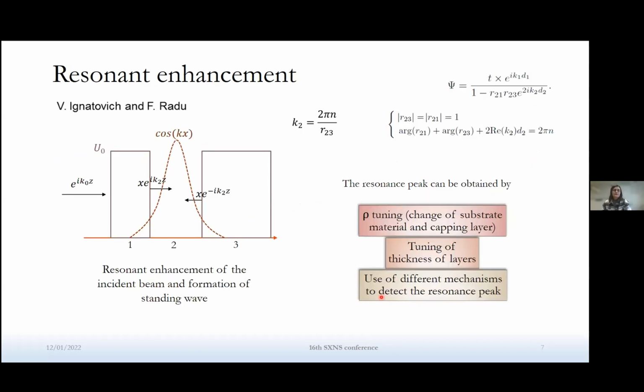So what do we mean by resonant? The idea is not new. It was first introduced by Ignatovich and Radu, and that is to have a resonant enhancement of the neutron wave density at the depth of the host material. In principle, the principle is similar to that of a particle in a box with finite walls that we all know from quantum mechanics. So we have a particle, which in our case is the neutron, which interacts with a potential that in our case is the scattering potential formed by our layers. Now, if this potential has the shape of a well, as here in that example, the neutron gets somehow trapped in it and forms a standing wave as a solution of the Schrödinger equation.